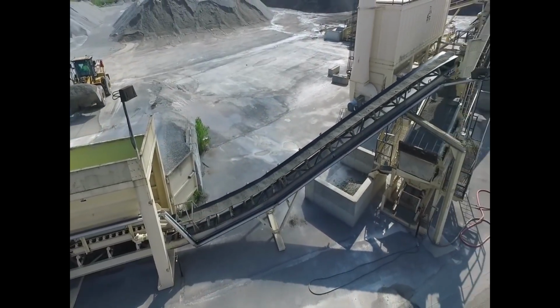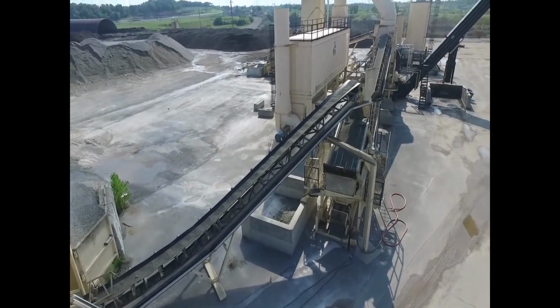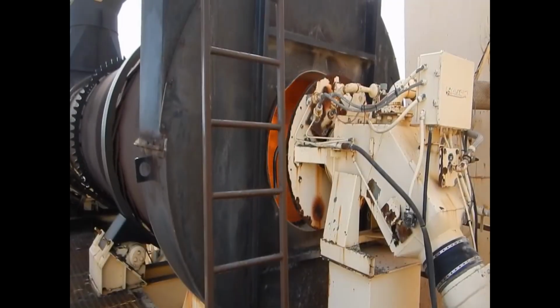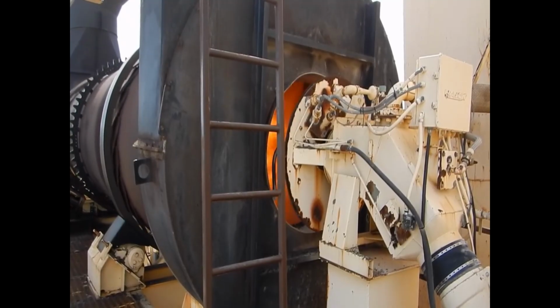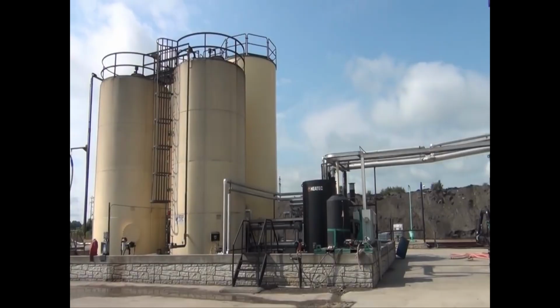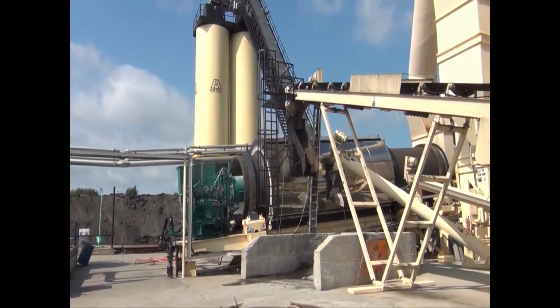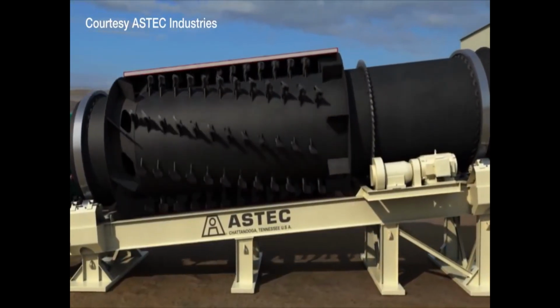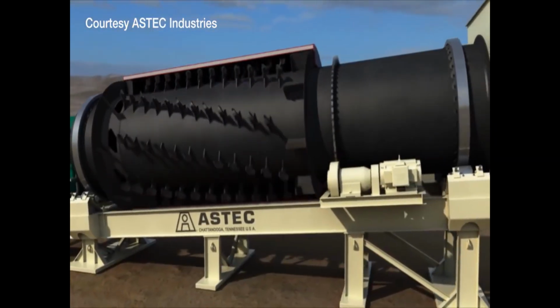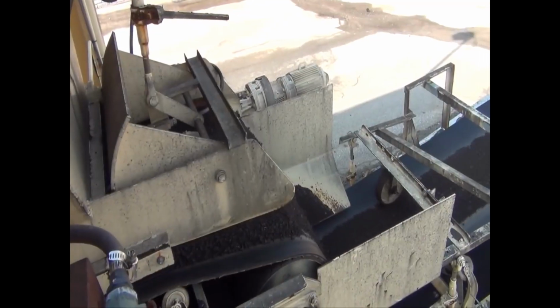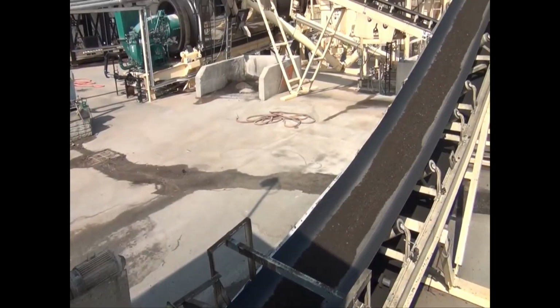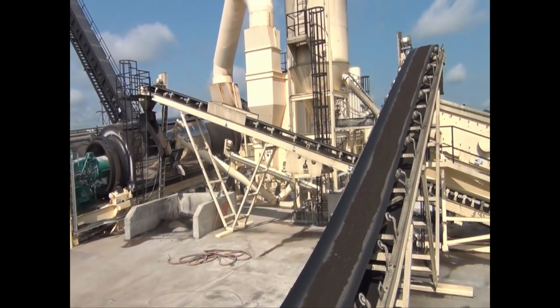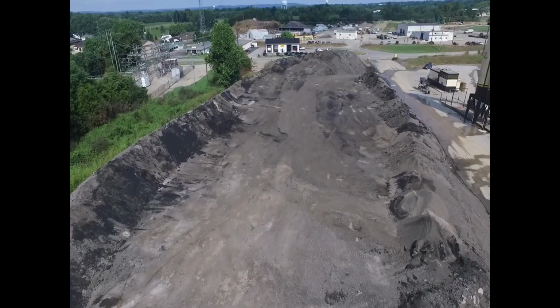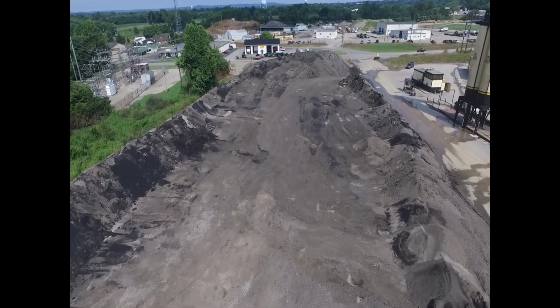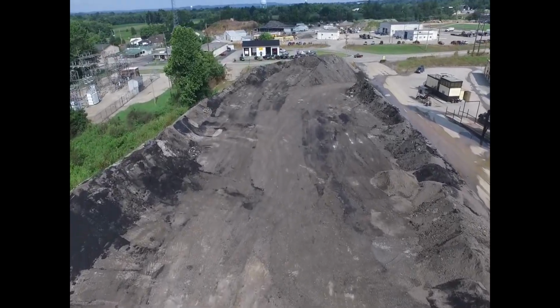Usually, the aggregate enters a large rotating drum with a gas-powered burner flame on one end. The aggregate is completely dried by the burner. Once that happens, liquid asphalt is pumped from the heated storage tanks and added to the drum, where the rotation mixes it with the aggregates. Reclaimed asphalt pavement, or wrap, can also be sent to the drum through a separate cold feed bin and conveyor. Using these recycled materials reduces cost and is friendlier to the environment.